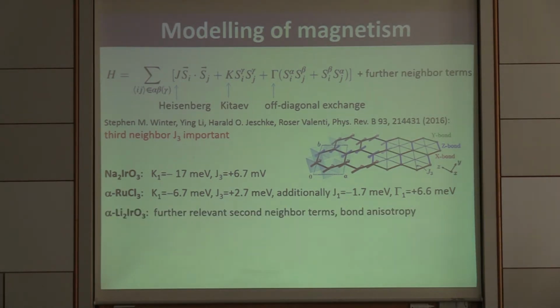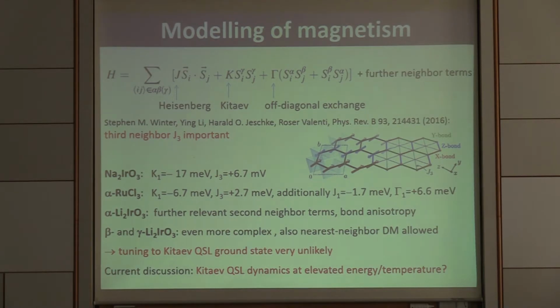Now, for the alpha lithium iridate, in addition to those terms, there are also strong second neighbor terms, also a second neighbor Kitaev term, which causes this complicated, complex ordered structure. There is also indication for bond anisotropy, meaning that the Kitaev terms are different along the three different bonds. For the three-dimensional versions, the beta and gamma lithium iridate, the situation is even more complex, and there are even next neighbor Dzyaloshinskii-Moriya interactions included. So from these considerations, it's highly unlikely that we can tune these materials into the Kitaev quantum spin liquid ground state by just applying pressure or changing the chemical composition.